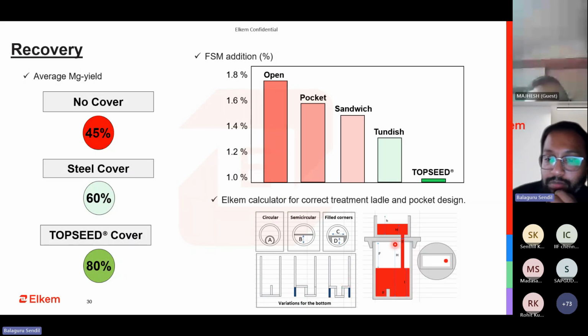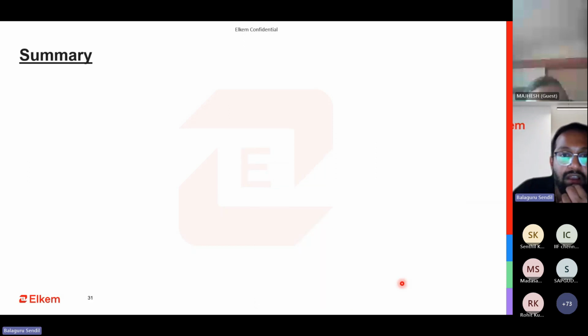We can calculate what should be this height in your tundish capacity, how much it can hold, so that you have a very uniform flow here. All these things, if we can go in detail and check, will make sure that your recovery is on the higher side. You can use the least amount of magnesium, and in the least amount of magnesium also, you can use the lowest grade of magnesium. So this is with respect to the recovery.